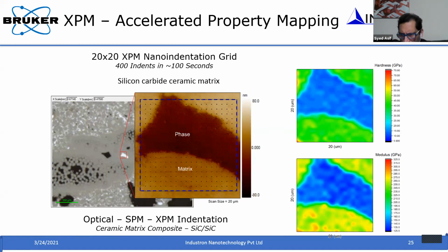Okay, so here you can see the hardness map of this one small region where you see some kind of a phase, and then the matrix. Here you can see the indent placement. The top part shows the hardness map. The image is pretty much revealing what is happening there. You can see how the hardness is different at different regions. The same thing, you can also see in the modulus, and you can see at the boundary how the modulus is gradually changing. You can see that from the color rendering pretty nicely.